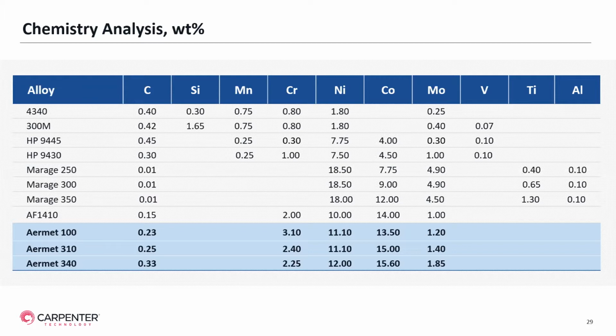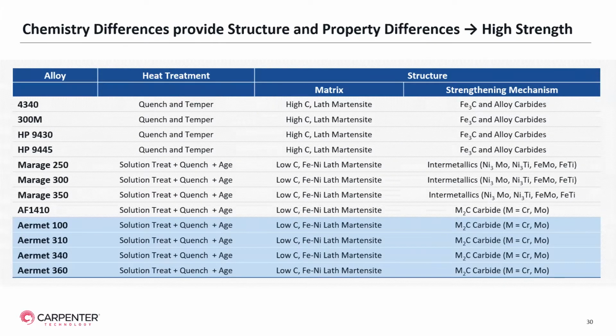And as we discussed, that also provides added cost, but that added cost provides very key strengthening elements. If you go to the very next slide, we can talk about how those chemistry differences provide the added high strength. The original 4340 and 300M are just quench and tempered alloy with high carbon lath martensite. Your strengthening mechanisms are just iron carbides and alloy carbides. As you go up adding nickel and cobalt, you get higher strength. Going into the Maraging steels and the Aermet alloys, you've got intermetallic phases, and the Airmets provide us our M2C carbides for additional strengthening.